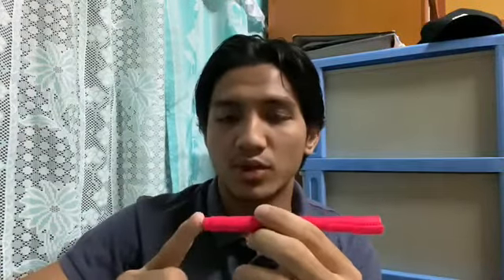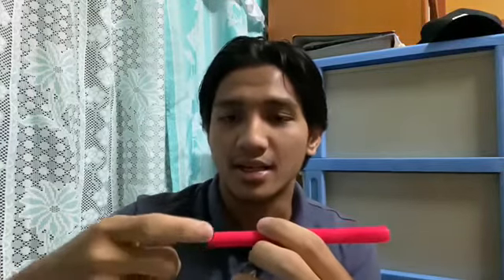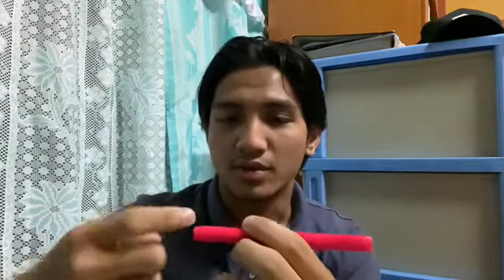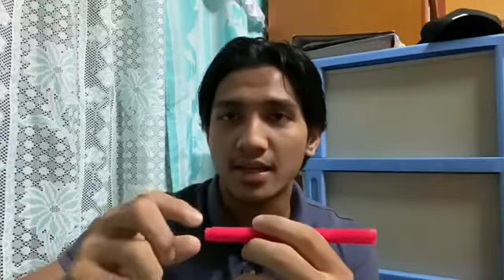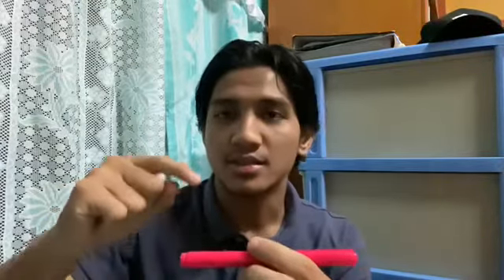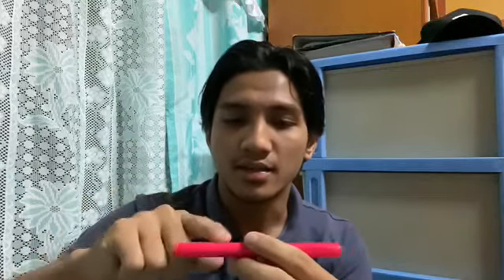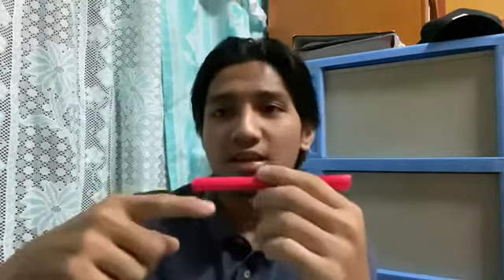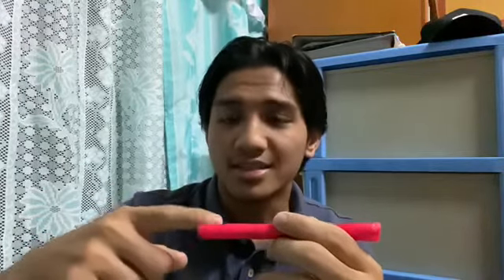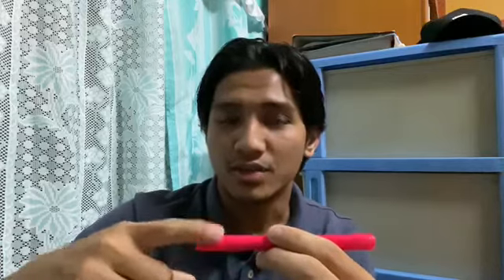We know that only one end has been quenched by water, so it has the highest cooling rate among the other points. So we expect that at this point the hardness level is the highest, because it has the rapid cooling rate compared to the other points that have been marked. This is because at this spot, the quench end of the steel, the structure has been fully transformed to martensite. Hence, it will have the highest level of hardness.